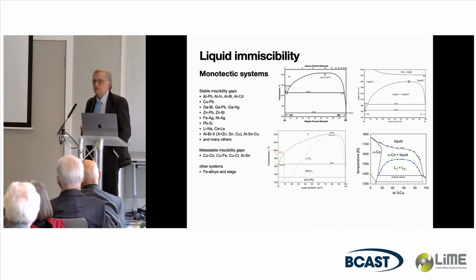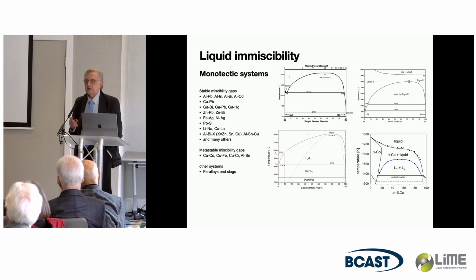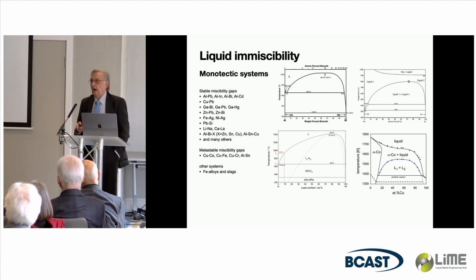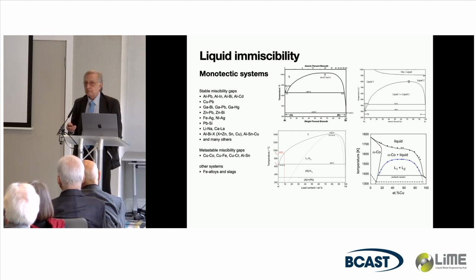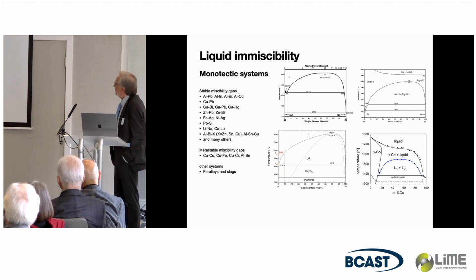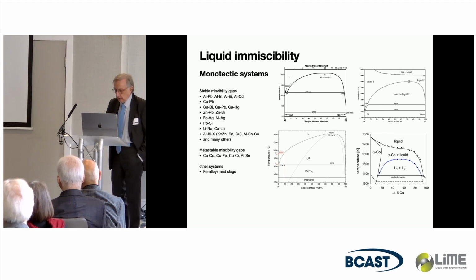Important, and it was mentioned this morning, that iron slags are also immiscible. So, for instance, if you deoxidize iron with silicon, iron-silicon mixtures, then you form silicon oxide, and silicon oxide is liquid in an iron melt. So I have a liquid phase in a liquid matrix.